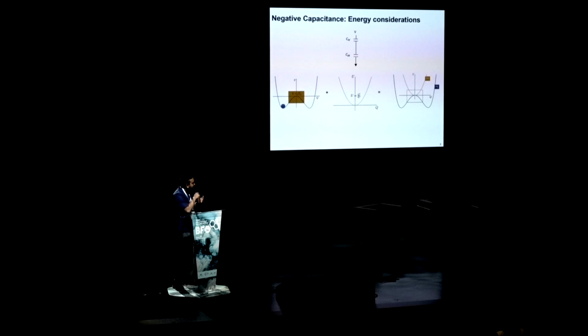Energy is a scalar. So if I put some positive energy in the system, let's say I put another dielectric which has a parabolic energy landscape, just Q square over twice C, then I'm adding this W of a ferroelectric with this parabola of a dielectric. And if my addition is appropriate, I will get this green curve. That is the composite energy landscape. And for this composite energy landscape, the minimum energy point is actually here. Okay, so locally, the ferroelectric is sitting in a region where the collective energy dominates and my capacitance is negative. Locally, right? It's not globally. Globally, the material is still in its minimum energy position. But locally, the ferroelectric has to go there to minimize the overall energy in the system. So that was a very simple way of trying to push the material in this region where it by itself doesn't want to go. Okay.